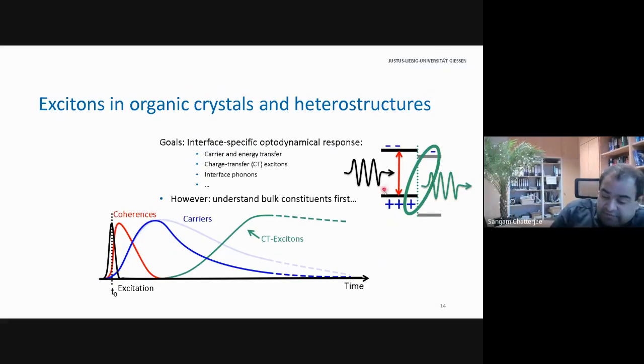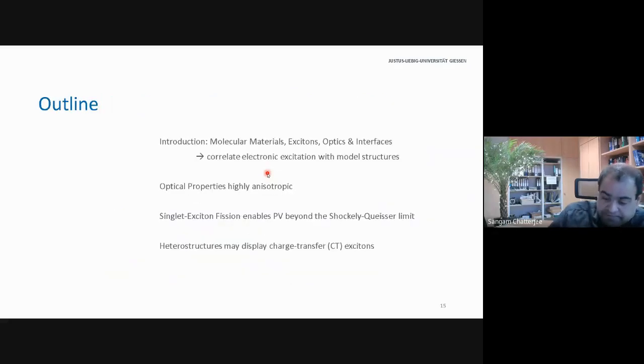So adapting the time scales we had before, what we expect here is we have an excitation which has a coherence which will form charge carriers. And these charge carriers will actually form excitons in these light blue lines, and we'll come to excitons again in a second. And having the interface around will change the carrier dynamics of the individual constituents considerably, because the interface can open new relaxation channels which are not there if you just look at one individual bulk part. And therefore, you see from light blue to dark blue, you get a change, and you see a charge transfer state, for example, pop up.